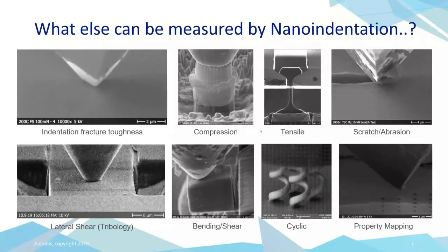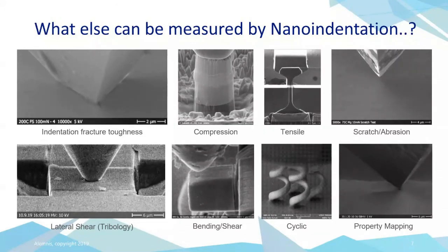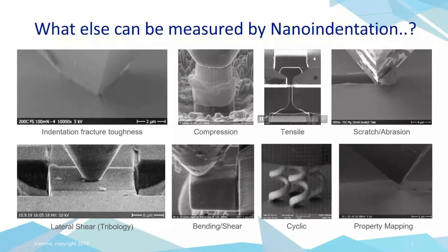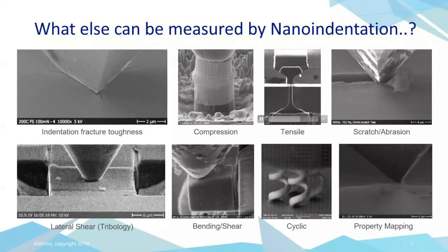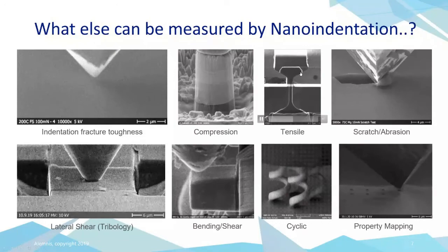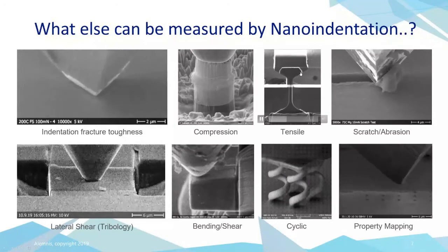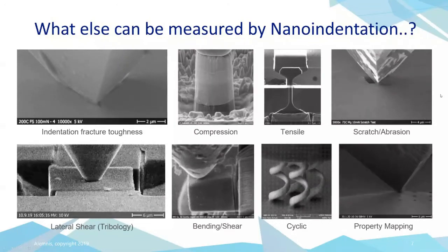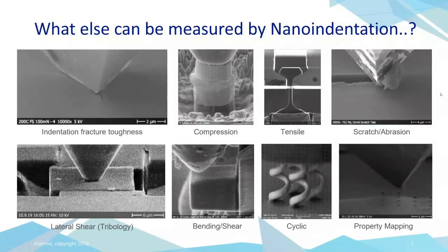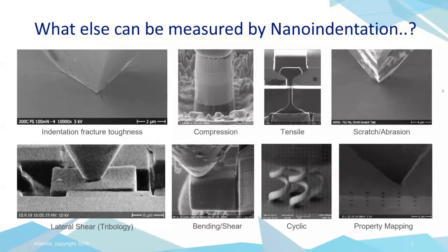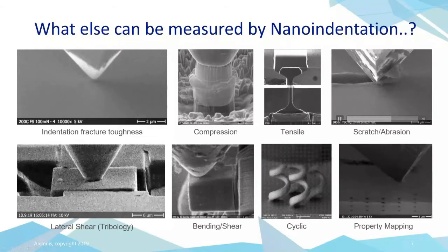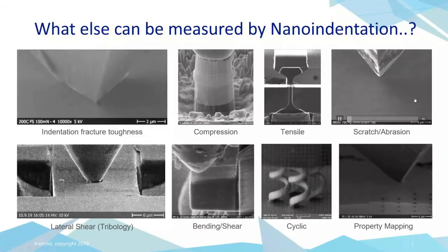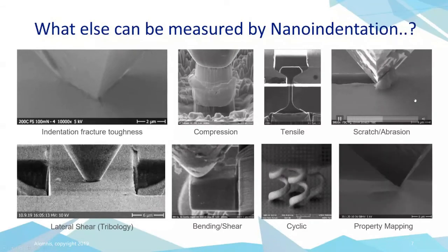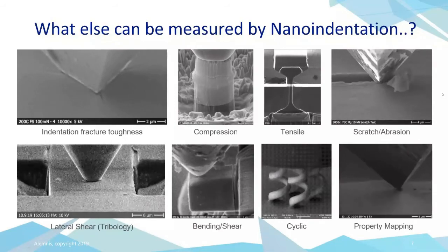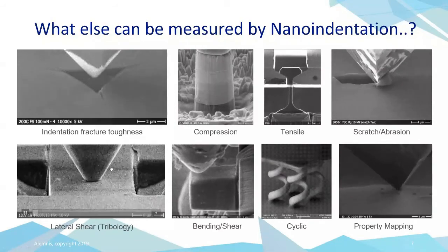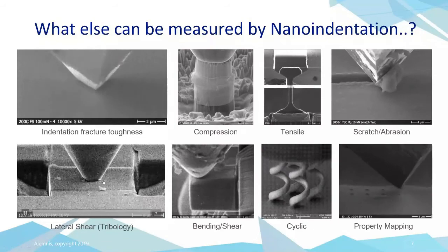Alemnis indenters work in both compression and in tension. So for tensile testing, we have a gripper kit that can pick up a FIBed tensile specimen and therefore do a tensile test at the small scale. We have a lateral force sensor to be able to do scratch testing. So scratch and abrasion of the surface, and also investigating how material recovers after scratching, which is very important in aesthetic applications.